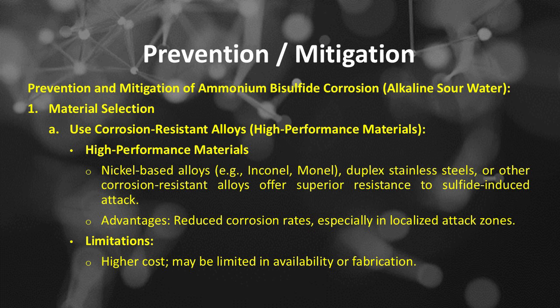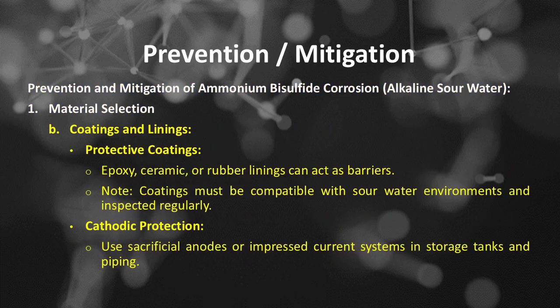Prevention and mitigation of ammonium bisulfide corrosion in alkaline sour water includes: Number 1 is material selection. Number A, use corrosion-resistant alloys. High-performance materials include nickel-based alloys such as Inconel, Monel, duplex stainless steels, or other corrosion-resistant alloys, which offer superior resistance to sulfide-induced attack. Advantages: reduced corrosion rates, especially in localized attack zones. The limitations of using corrosion-resistant alloys: higher cost, and they may be limited in availability or fabrication.